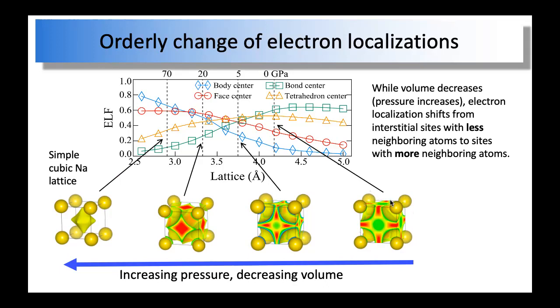Okay, so let's say we take a simple cubic lattice of sodium, and we start at the lattice parameter of 0 GPa, but this 0 GPa is actually the BCC sodium lattice constant at 0 GPa. So basically we take BCC sodium and we remove the atom at the center, and then we have this simple cubic lattice, which has the same lattice parameter as the BCC sodium. And if you calculate that, you can see that the electron is very much localized at the bond center. However, it also has a large value at the face center, right? So if you compare those two values, the value in between is here, right?